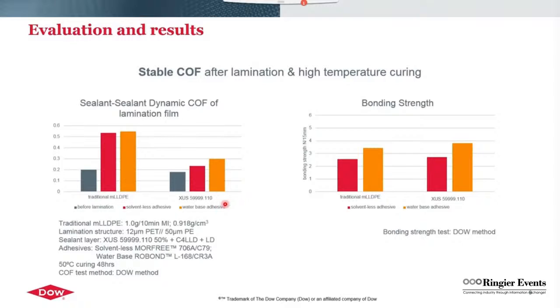A graph on the left-hand side shows the COF of the polyethylene film before lamination and the COF of the laminate after lamination and curing. The lamination was performed using both solventless adhesive and water-based adhesive. The results show that before lamination, the COF of the polyethylene film for both sealant formulations was about 0.2. After lamination and curing, the COF of the traditional metallocene LLDPE sealant increased to above 0.5. While for the formulation with the COF stable resin XUS 59999.110, the COF was maintained at 0.3 and below. This shows that the COF stable resin XUS 59999.110 can help to maintain low and stable COF after lamination and curing.